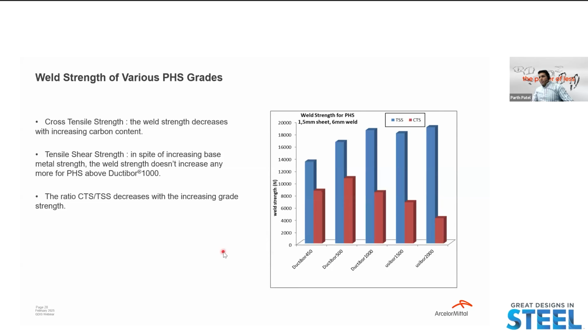Another thing I want to quickly touch upon is PHS grades the weld strength. Obviously TSS, tensile shear strength, because this is all fully martensitic. Ductibor 1000, 1500 and 2000 is fully martensitic. We haven't seen any effect of the carbon, but for cross tensile test, it has an effect of carbon. As carbon percentage increases, Ductibor 1000 has around 0.1, this has 0.22, Usibor 2000 has around 0.34 typical value. And as carbon percentage is increasing, your cross tensile test is decreasing. This has correlation with the toughness of the weld, which I'll discuss in the next slide.